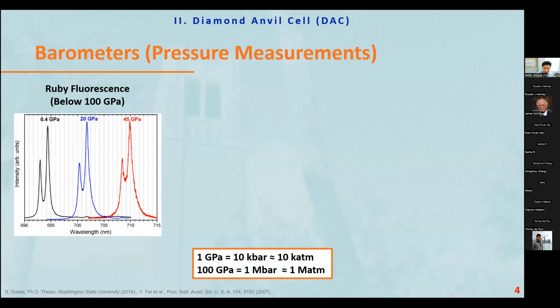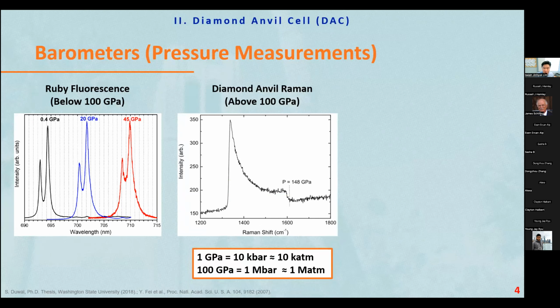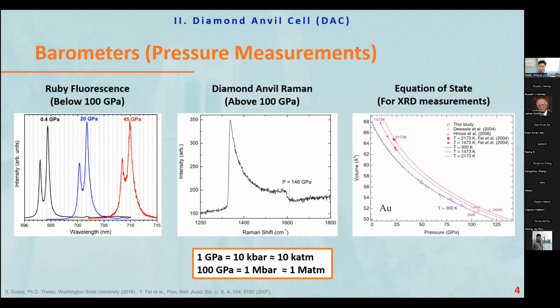So how do we measure pressure? Yeah, I think everyone in this high pressure community knows that we mostly use ruby, and also we use diamond anvil Raman for the higher pressure, and we use gold or other well-known pressure markers with a well-known equation of state for X-ray diffraction measurements and so on. And what I like to emphasize is my expertise in this electrical resistivity setup in the diamond anvil cell.